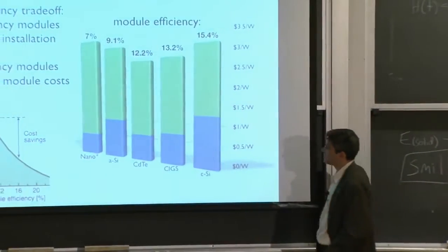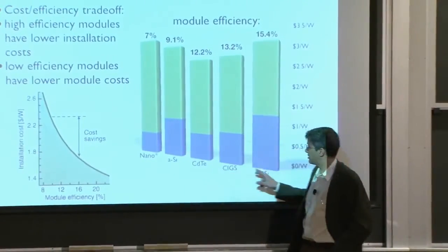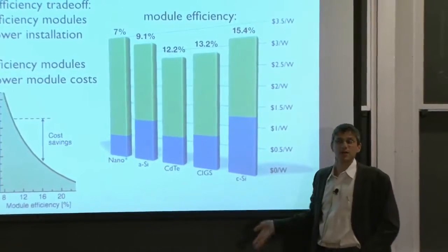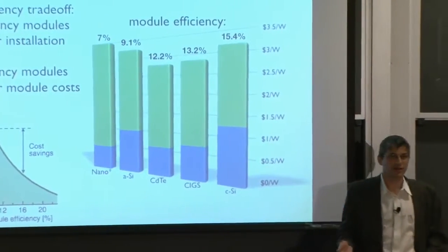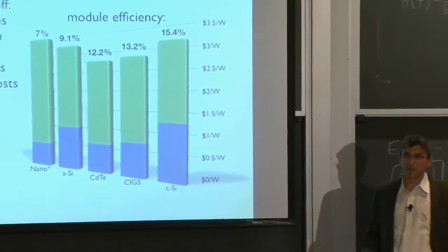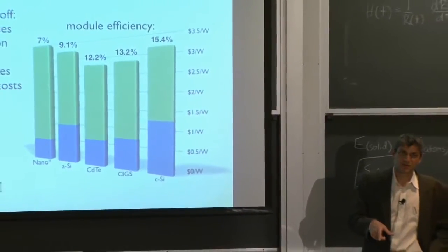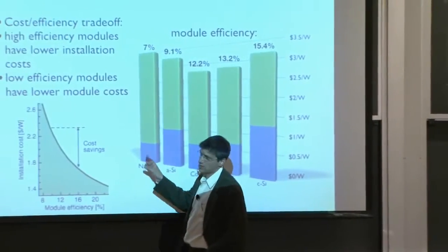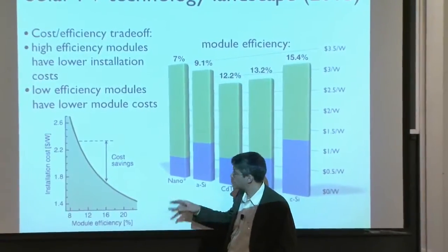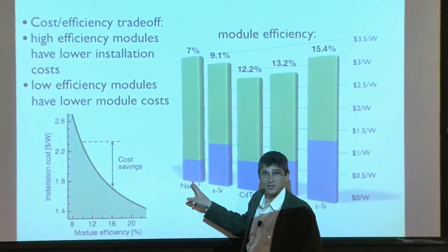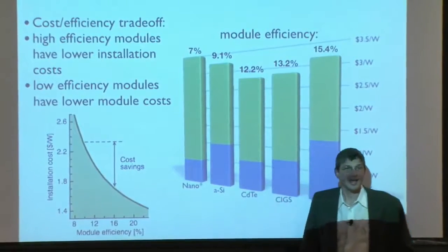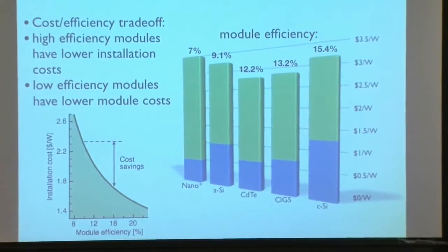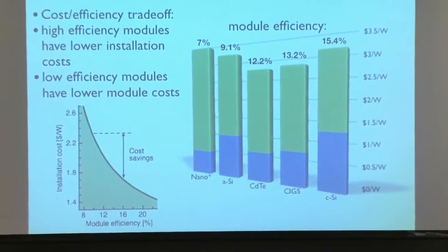You can make amorphous silicon at a micron. You've got to make this at 100 microns to absorb all the light. If you don't make it that thick, it just won't absorb enough light. Why isn't it absorbing light? The band structure tells you. The band structure, or these electron states, would also tell you that for nanostructure PV, you can make them as thin as 50 to 100 nanometers and absorb all the light. That's how efficient they can be at absorbing light.